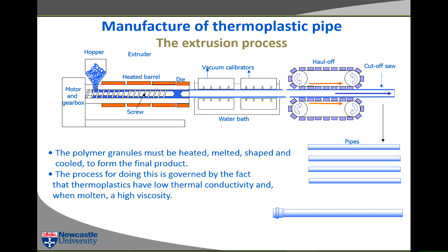Excuse me. You're saying that a lot of the energy is transferred to the plastic through the motor and the gearbox. Yeah, the rotation. So what kind of speed are we looking at for the extruder? The screw is running usually at about 2 revolutions per second. So it's 100, 120 RPM. So it's not really fast, but it's sufficient.